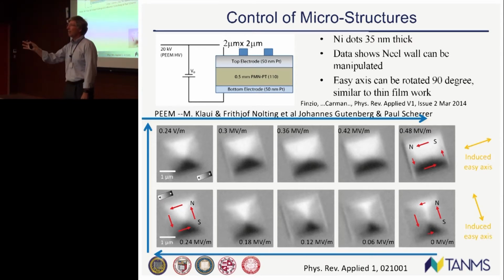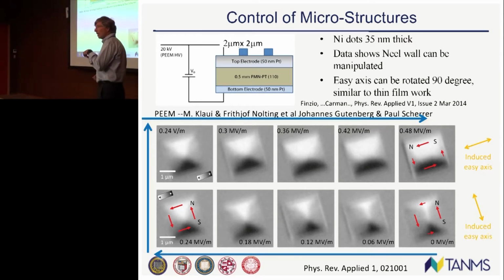Let me teach you something about PEEM, okay? So they shoot X-rays in, and if the X-rays are parallel with the spins, that means it's white. If the X-rays coming in are 180 degrees away from the spin, that means it's black. Now if the X-rays coming in are 90 degrees to the spin, that means it's gray. So this 2 micron by 2 micron bit of nickel actually has closure paths, goes north-south, north-south, north-south, north-south. And if you look, it has a prominent easy axis along this direction.